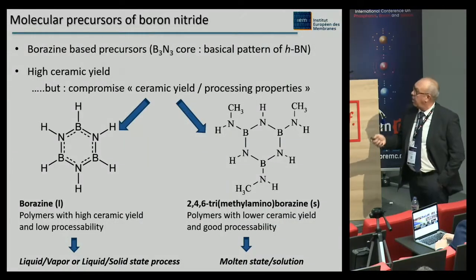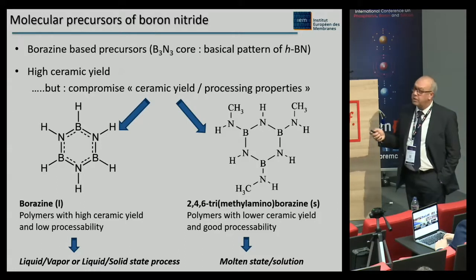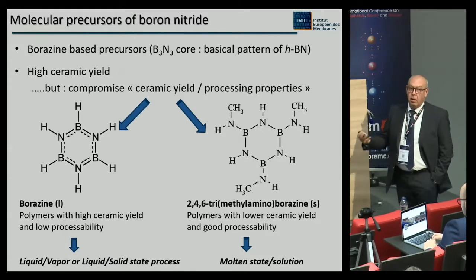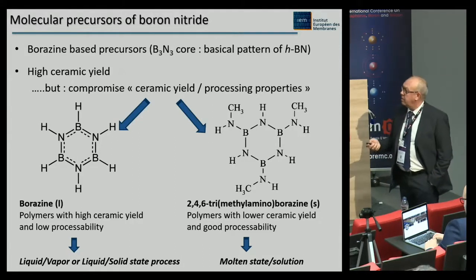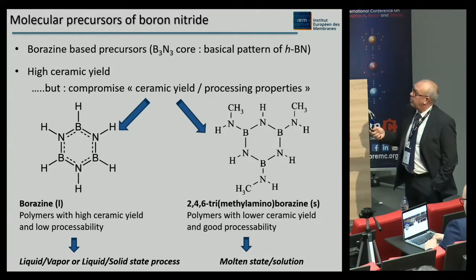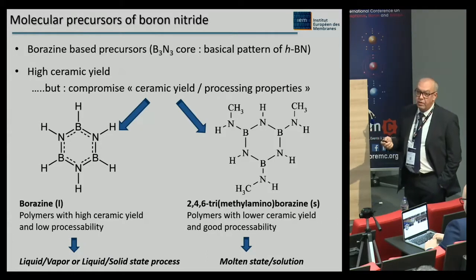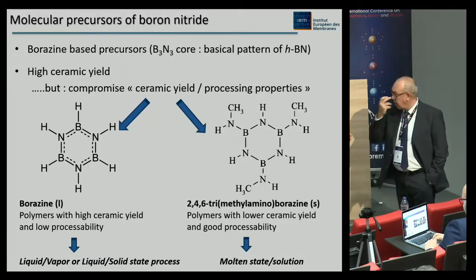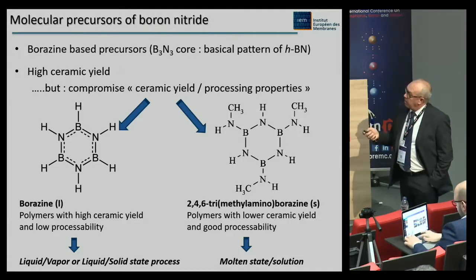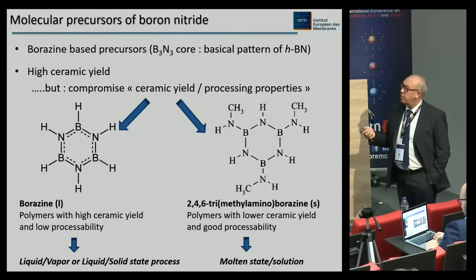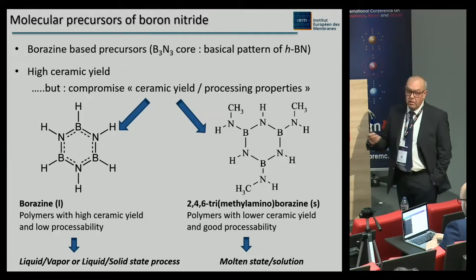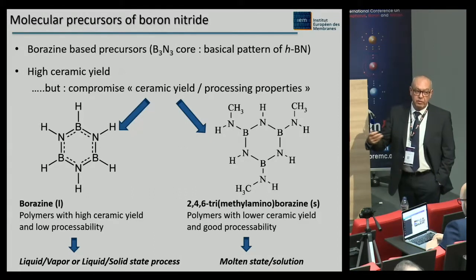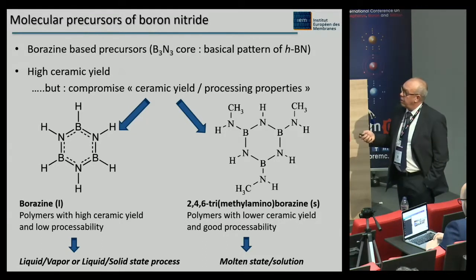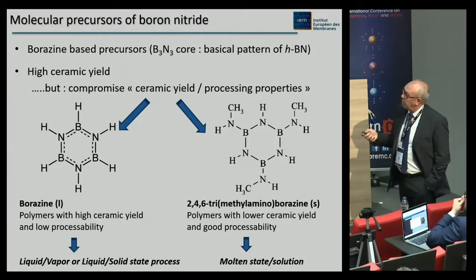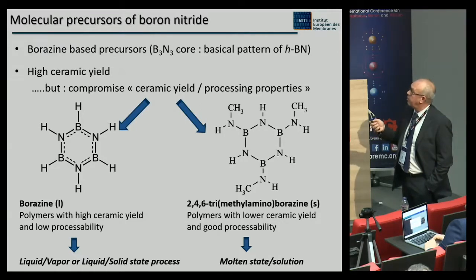Now, a few words about the precursors. The precursors for BN are mostly based on borazine, which is the well-known inorganic analog of benzene. The reason is that borazine displays a B3N3 core, which is the same as in boron nitride. And you have to pay attention in the ceramic world to what is called the ceramic yield, meaning the weight of ceramic at the end of the process compared to the weight of the precursor. So these precursors usually display a high ceramic yield, but you will see that we always have to find a compromise between the ceramic yield and the processing properties.